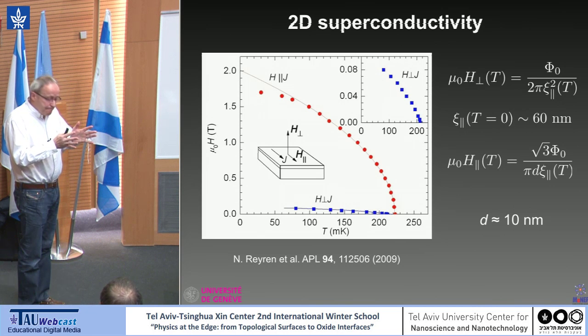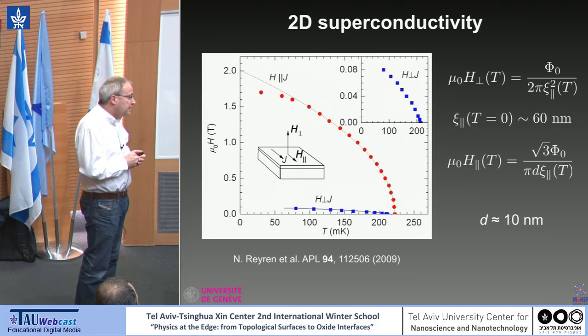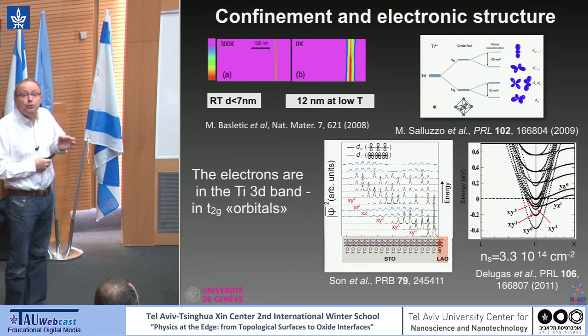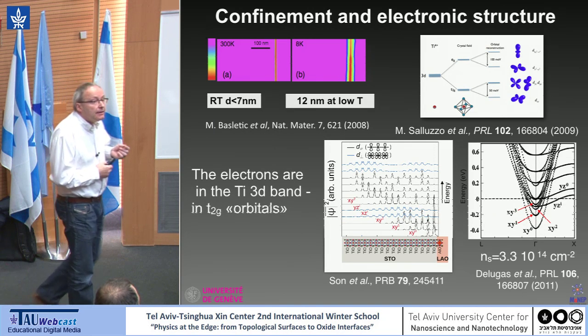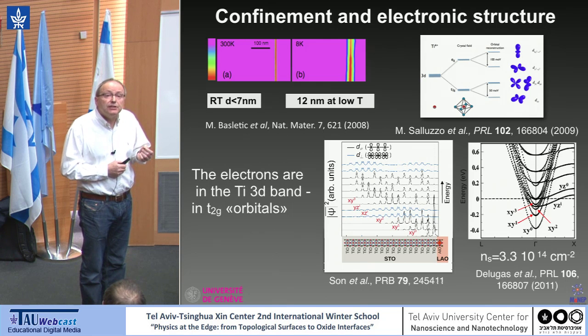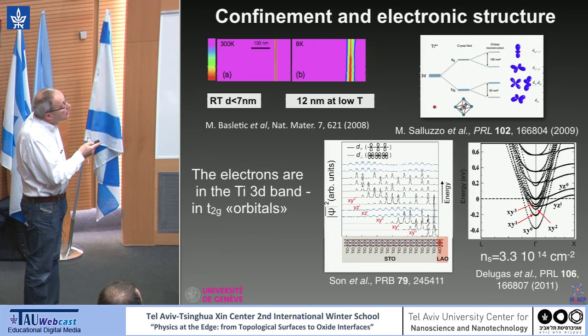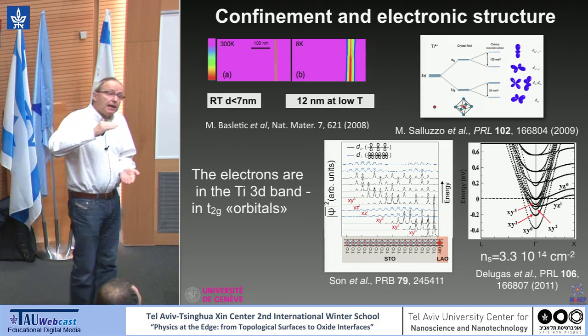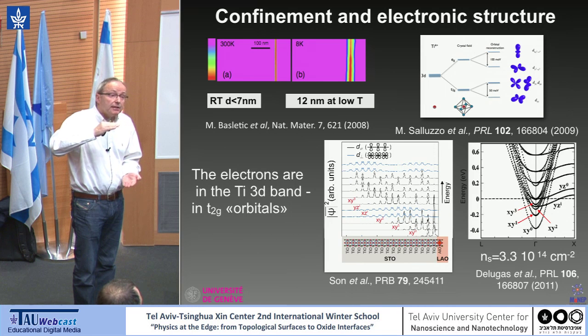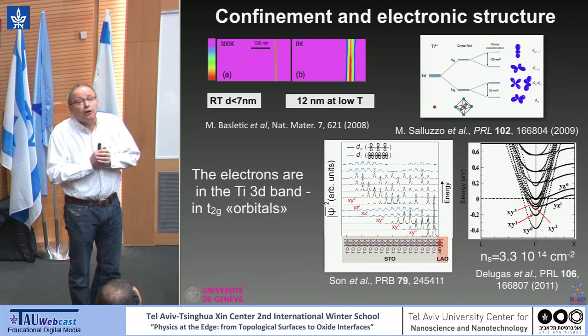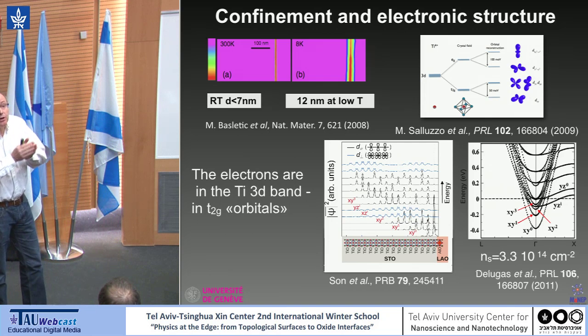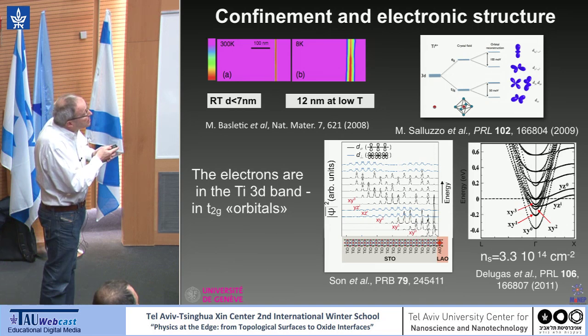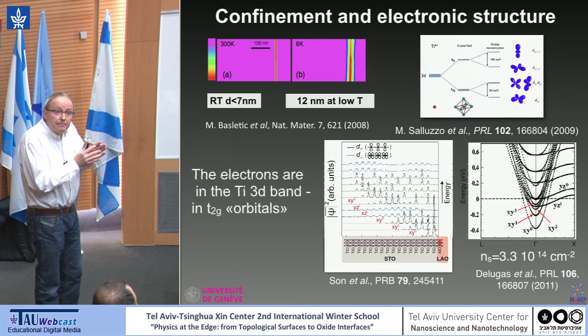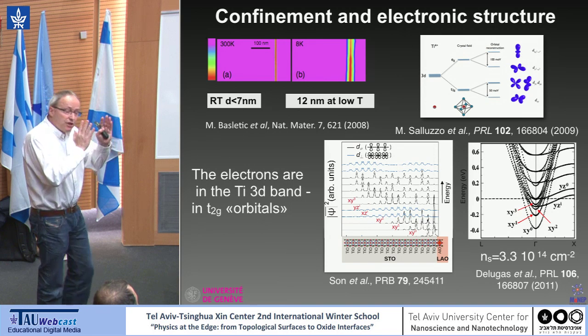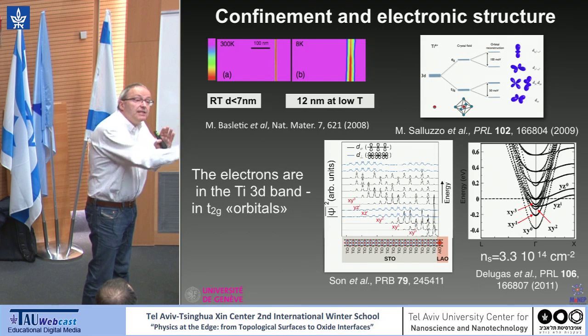OK, so we have a conducting layer which is confined within a distance of about 10 nanometer. And there are 2 consequences. The first one is that this confinement is lifting the degeneracy of the t2g orbitals. In a perovskite structure, if you look at the d band, you have the t2g orbitals and the eg orbitals. The eg are pushed at much higher energies by crystal field splitting. And this is simply due to the fact that the lobes for the eg orbitals are pointing towards the oxygen, and so this is more costly in energy. In a cubic structure, the t2g are degenerate. But here, the xy orbital, which is parallel to the interface and which allows easy conduction, is lower in energy.